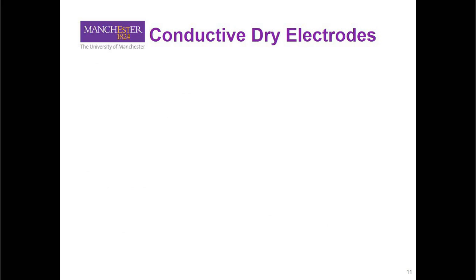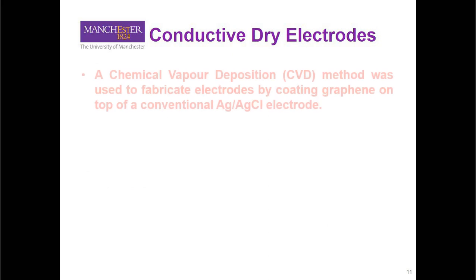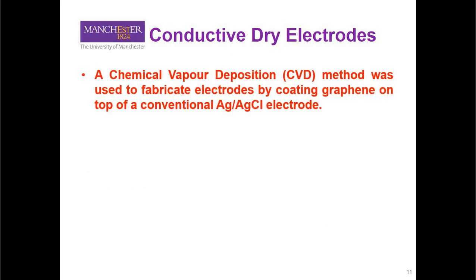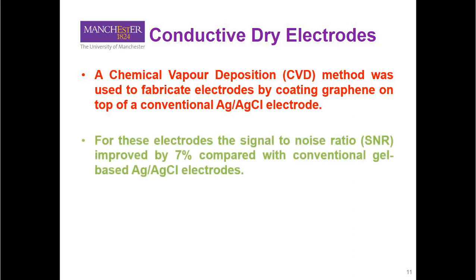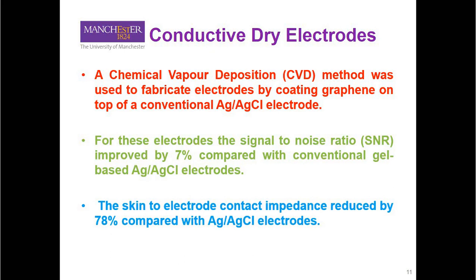Now, let me talk in detail about each type of graphene-based material electrode. The first type is the conductive dry electrode. In terms of manufacturing, chemical vapor deposition is a method proposed in the literature for producing conductive dry electrodes, and this method was used to fabricate electrodes by coating graphene on top of the conventional gold standard silver chloride electrode. For those electrodes, the signal-to-noise ratio improved by 7% compared with the conventional gold standard ones, and the skin-to-electrode contact impedance reduced by 78% compared with the gold standard one.